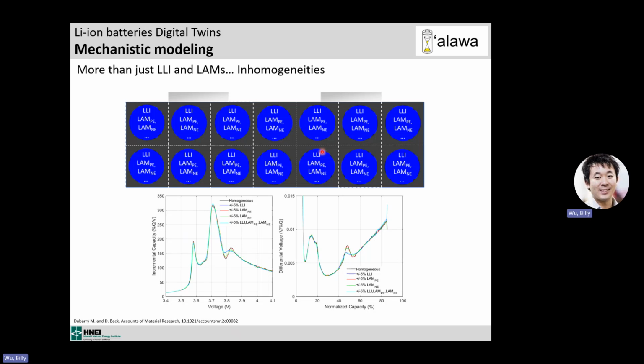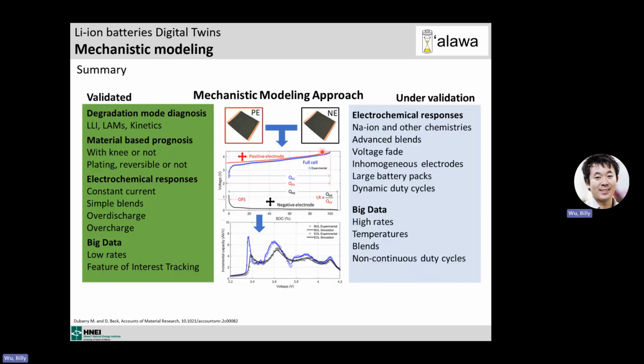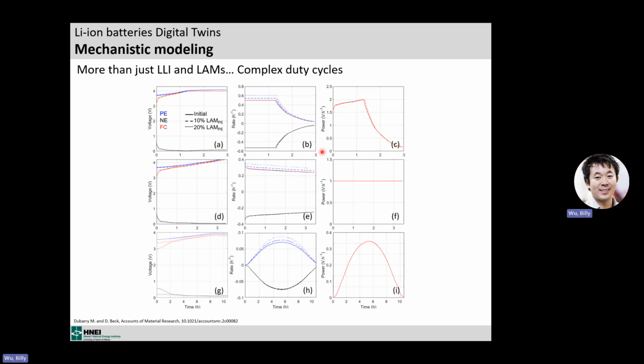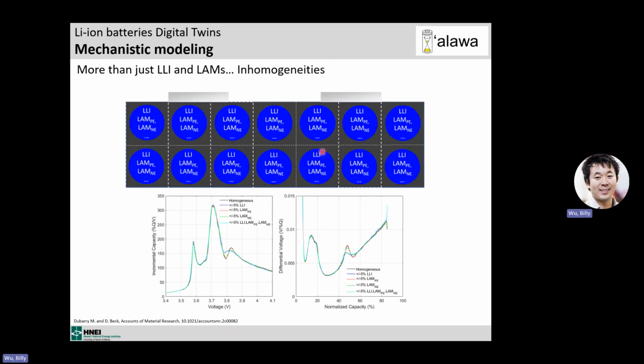But for a single cell, you also want to consider, and I don't have the slide here, but we just published a paper where we also consider the paralleling at the electrode level. And look at the difference at the full cell when you do the paralleling using small full cells or do paralleling at the electrode and then calculate the full cell. It's not the same thing. And which one happens in real life? When you rest, the paralleling is only at the electrode level. But when you use the cell, both of them are probably happening at the same time. And that influences the voltage response of the cell.